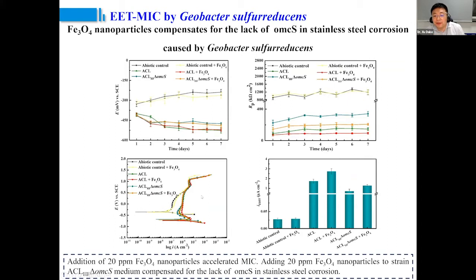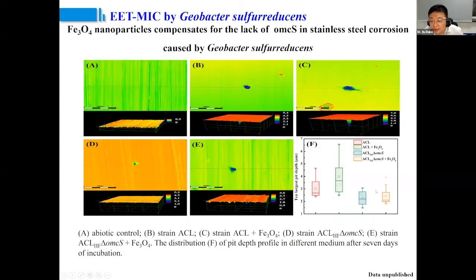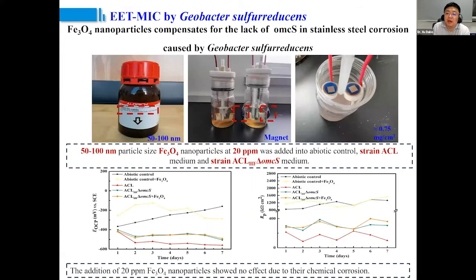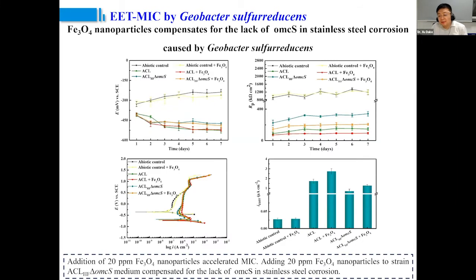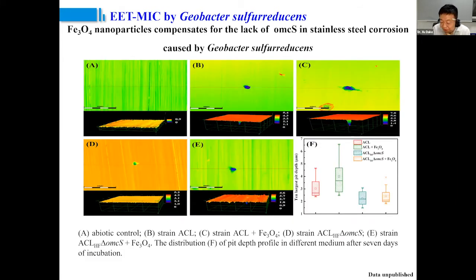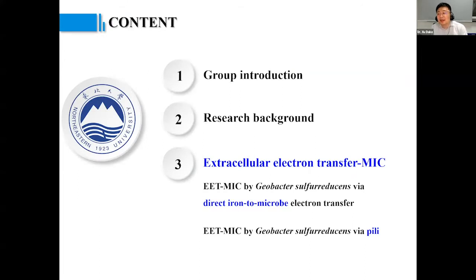This can be verified by the polarization curve. We can see when we add nanoparticles, the corrosivity increased. And the same data obtained by the pitting morphology examination is highly consistent with the electrochemical data. Oh, I think we also have the weight loss data. Because I just made the presentation, please forgive me. The weight loss data is also fully consistent with our conclusion.